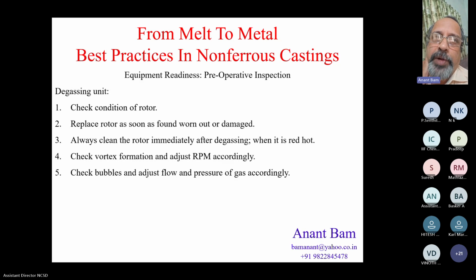But by thumb rule, if such bubbles break on the surface of the molten metal, then naturally very tiny aluminum metal particles are spattered outside the crucible, and they get collected on the top of the furnace lid or furnace cover. These particles appear like suji or semolina. In Marathi, we call it rava. In Hindi, we call it suji. And it appears like very small shot blasting shots, maybe 0.3 to 0.4 mm in size.